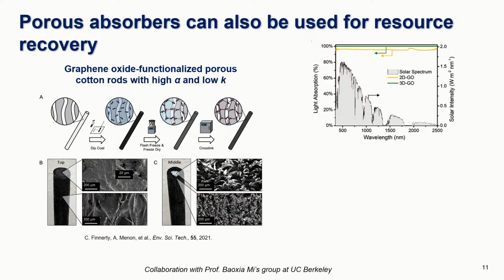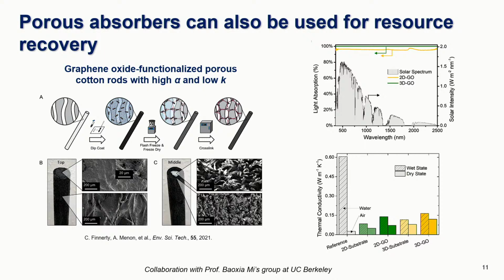The light absorption for this 3D graphene oxide is the green line. So almost 100% light absorption. So a very, very good solar absorption across the entire solar spectrum. And at the same time, we can maintain a low thermal conductivity. And so here again, showing the thermal conductivity remains pretty similar to the cotton itself. So the graphene oxide does not impact the thermal conductivity significantly. And so we're able to stay under that 0.15 watts per meter Kelvin, so still fairly insulating. And so we're not losing that heat.